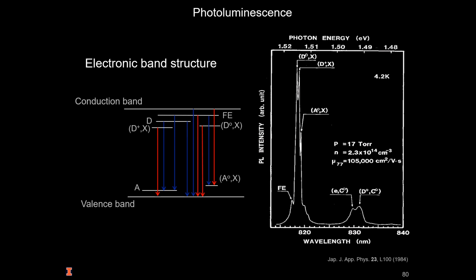Going to lower temperatures is one way to minimize that, but excitonic binding energies need to be taken into account. The Stokes shift on your sample needs to be accounted for when you try to fit or explain your photoluminescence spectrum.